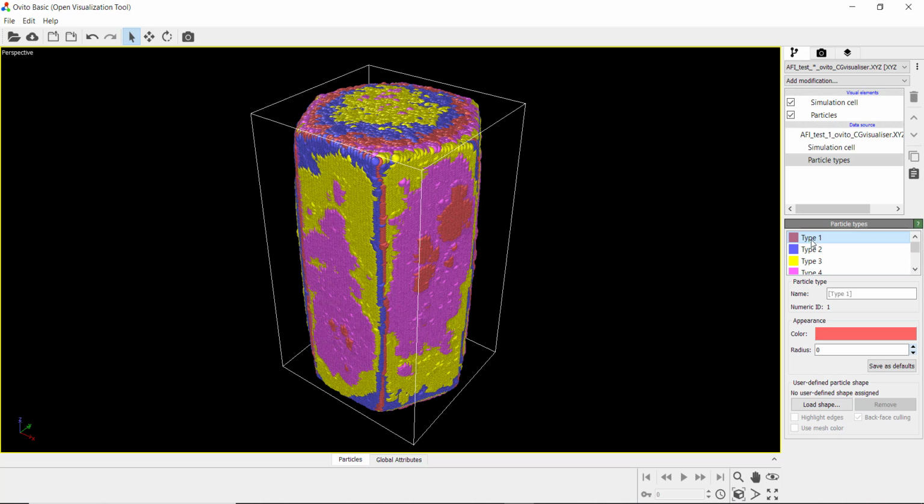You need to make sure you've got your facets file set up correctly to identify the surface of the crystal. And you want to try and get it as good as you possibly can, so identifying just the surface and not eating too much into the crystal. Then we've got our types greater than 100, so type 101 to 104 here. These are things that haven't been identified as part of a surface layer, but they're not fully grown units. So these could be our internal defects.